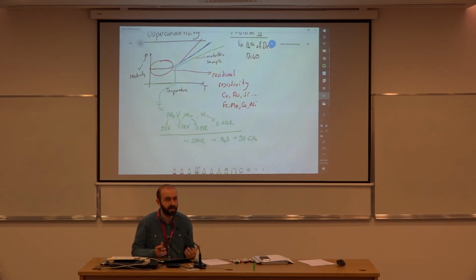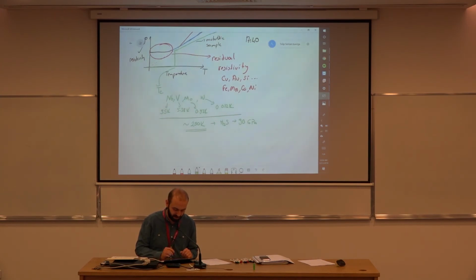H2S is actually a gas at room temperature. I cannot remember its freezing point, the temperature that it becomes a liquid, but I think it's pretty low. So they compress it to a point where it solidifies, and then when they measure, this is the record high superconductivity that has ever been achieved. But in a sense, it's useless because such high pressures are not practical. We have much better materials, actually.